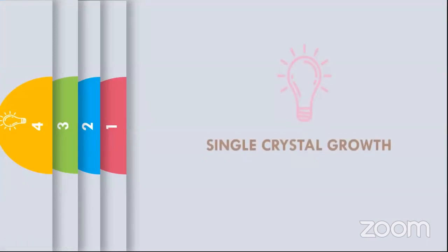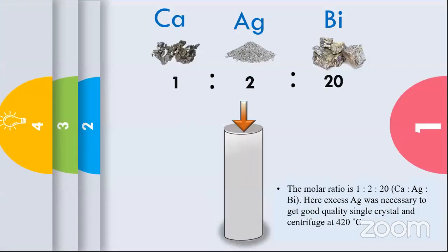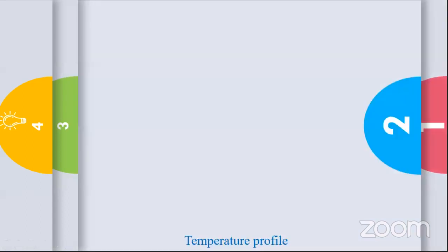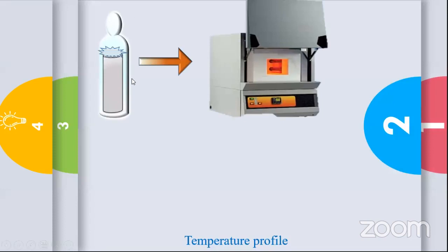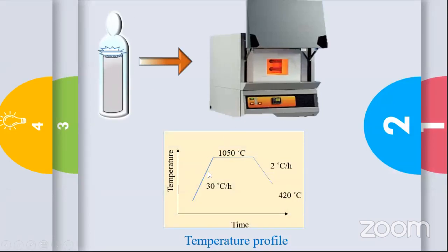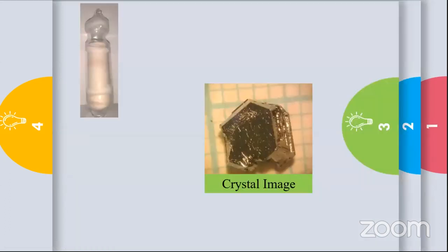To grow the single crystal, we followed the flux growth technique where we took calcium, silver, bismuth in a 1:2:20 ratio, and we took it in an alumina crucible and sealed it in a quartz ampule. We heated up to 1050 degrees Celsius at the rate of 30 degrees Celsius per hour, and stayed there for 24 hours. Then we slowly cooled down to 420 degrees Celsius at the rate of 2 degrees Celsius per hour. At 420 degrees Celsius, we centrifuged it, and we got a nice crystal of almost 1 centimeter size.